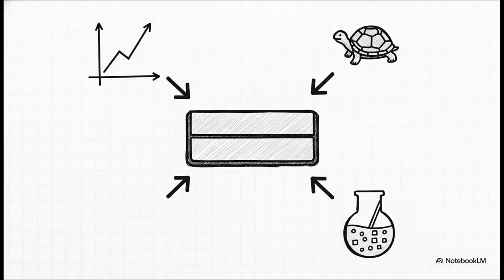Well, it's pretty clever. Engineers use the very principles we just talked about to get control. They can fight back against that supercooling by using a very steep temperature gradient, basically making it too hot for a dendrite to survive. They can also just slow the whole process way down, which gives those rejected atoms time to diffuse and wander away instead of piling up. And of course, it all starts by carefully choosing the elements in the alloy to begin with.